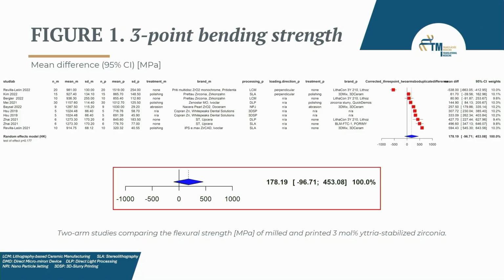We investigated, because this is a really prominent difference, and we found out that in this one, they used a different type of printing method, which is LCM, lithography-based ceramic manufacturing. We looked into why it could give us better results for printed zirconia than for milled zirconia. We came to the conclusion that this is a really good printing technique, which was invented by the Lithoz company, and this is unique to them. They developed a printer and they developed a material for it. So this is a closed system, and it can give us really high strength.